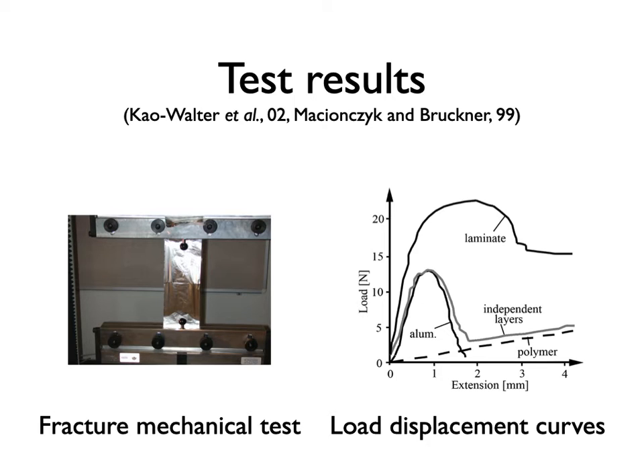The reason for the interest of these laminates is what you see to the right. You can see tensile tests made of this freestanding aluminium. See, that's the peak you see to the lower left-hand side of the graph. And then you see the polymer that is stretching, and the load that it carries is increasing, but the peak of the load disappears far to the right of this graph. So at these small strains, it isn't carrying much load.